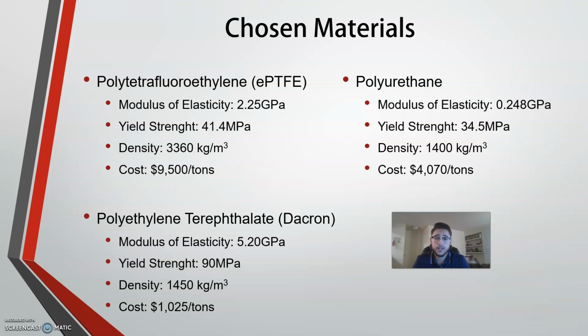EPTFE has a modulus of elasticity of 2.25 gigapascals, a yield strength of 41.4 megapascals, a density of 3,360 kilograms per meter cube, and a cost for this material of $9,500 per metric ton.